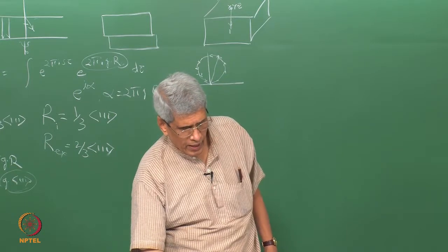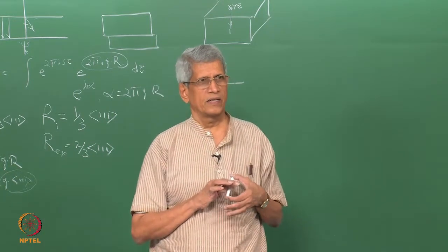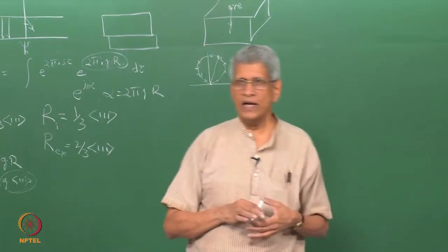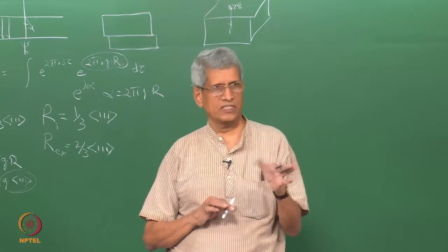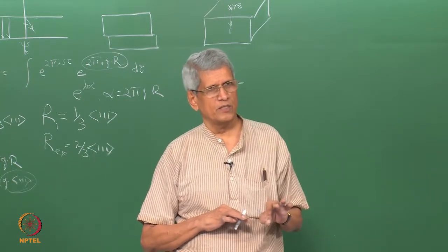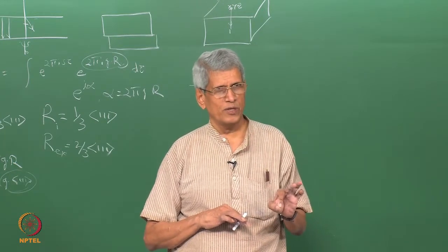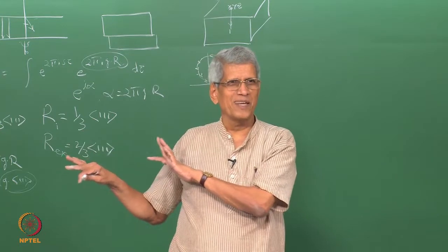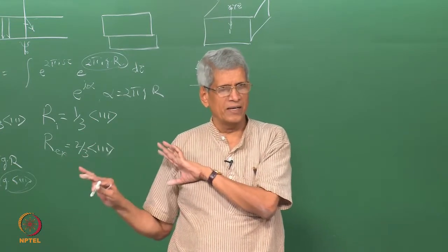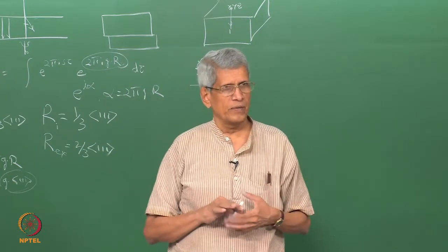Okay. There are many cases, in many complex alloys, where using g dot b you may not be able to identify the fault vectors uniquely. In such cases, computer simulation of the images has to be done. When you do computer simulation of images, you should know the full dynamical theory of contrast very well. There are software packages available, called the EMS package, with which one can do that.